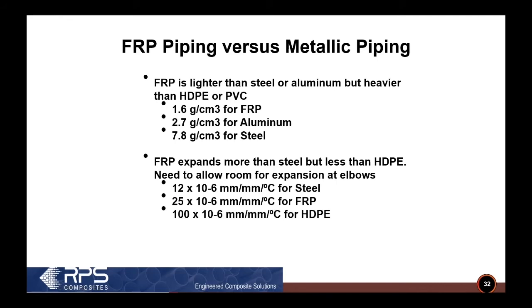FRP is lighter than steel, but heavier than HDPE. And usually that only comes into effect in actually handling the pieces of pipe. FRP is definitely handleable. You can pick up a piece of 6-inch pipe that would not be practical for steel, for example. FRP pipe expands more than steel, but less than HDPE. So if you look here, FRP has a coefficient of thermal expansion of 25 compared to 12 for steel and 100 for HDPE.